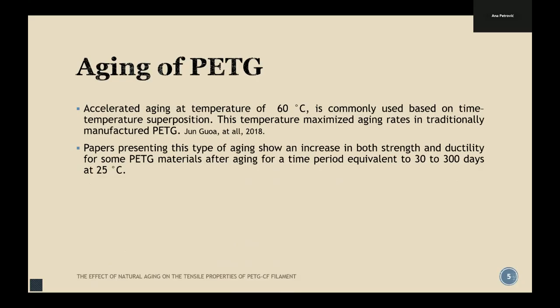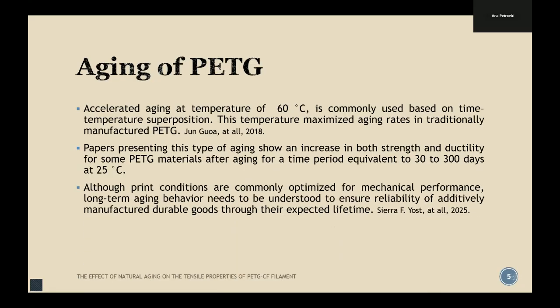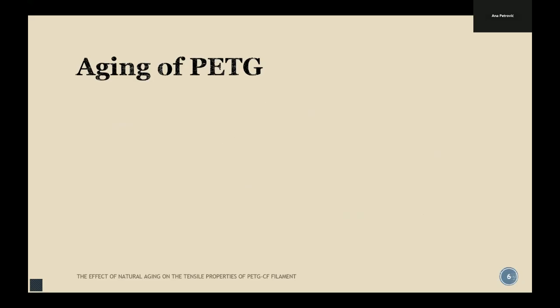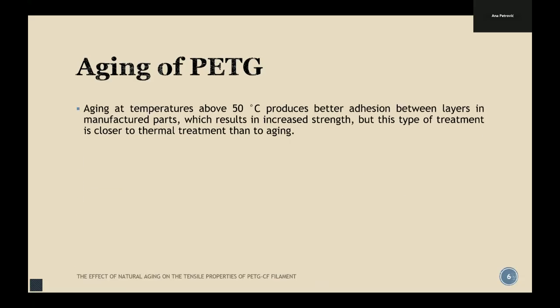Papers present this type of aging showing an increase in both strength and ductility for some PETG materials after aging for a time period equivalent to 30 to 300 days at 25 degrees Celsius, and we want to check that. Although print conditions are commonly optimized for mechanical performance, long-term aging behavior needs to be understood to ensure reliability of additively manufactured durable goods through their expected lifetime. This is also taken from a paper, and it makes very good sense, so we take that also as the start of our project.